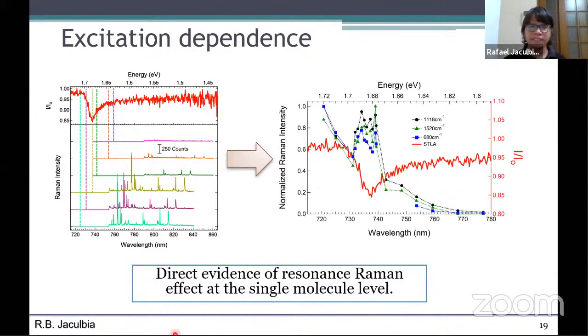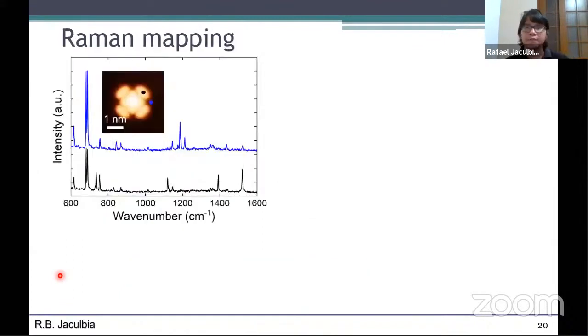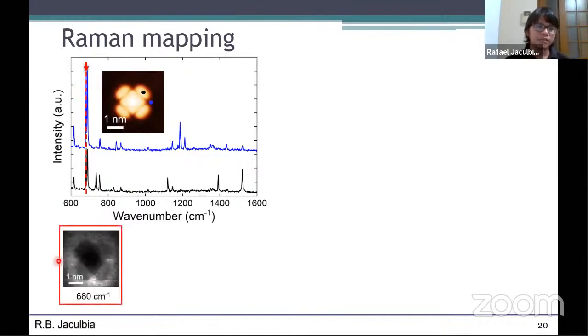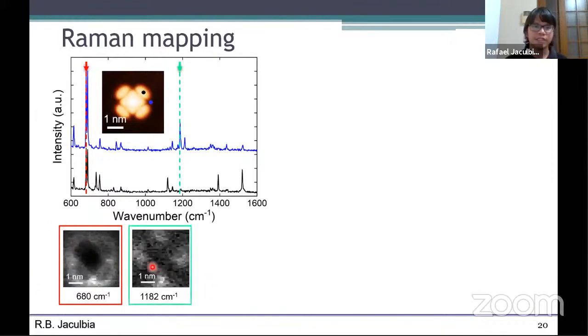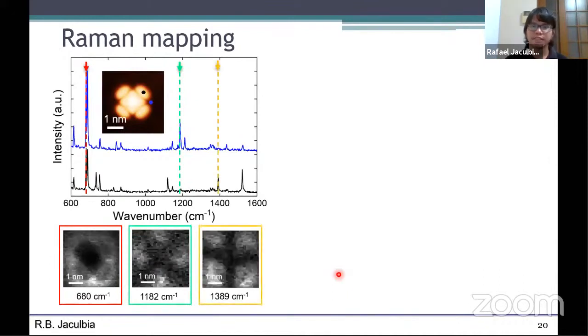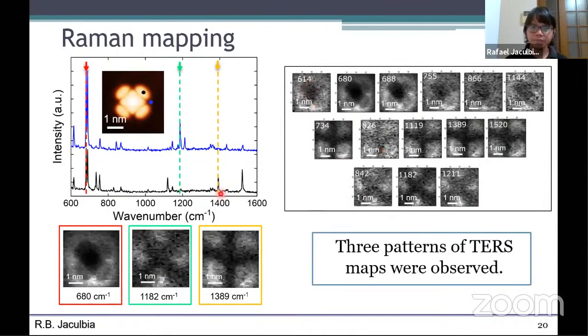So aside from this evidence of resonance Raman, we also tried to perform Raman mapping. We measured the Raman signal at several points of the molecule. Here, we can see that when the tip is placed between two lobes, this is the Raman signal. And when the tip is placed here, we can observe this Raman signal. So very clearly, these Raman signals are a little different. When we do the Raman mapping for this mode, we found this signal. For this mode, the Raman signal is like this. And in this mode, the Raman signal is like this. So we could identify 3 different patterns of the TERS maps for all of these vibrational modes.